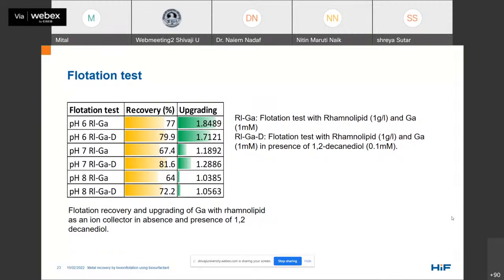Here we can see that the flotation tests were done at different pH in the absence and presence of gallium and decanediol. Now here in the table, you can see that the highest recovery of gallium is at pH 7, but there is another value in the table called the upgrading value. And we can see that the upgrading value is higher at pH 6 and not at pH 7, even though the recovery value is a little less.